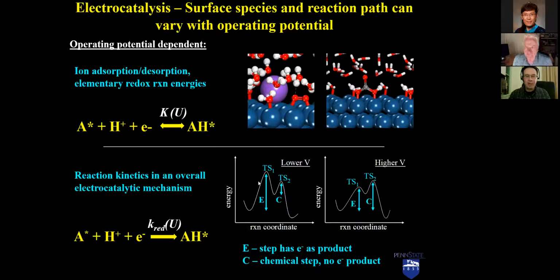Anytime we're trying to make out a catalytic reaction mechanism, or how the energy changes as we move from reactants to products, we are going to want to calculate reaction energies. If those were reaction free energies, then they would give us equilibrium constants. So we want to know elementary step equilibrium constants. Of course, we also want to know the barriers to reactions occurring. Those are activation barriers. And we'd like to then, of course, be able to relate those activation barriers back to rate constants. And if we knew the equilibrium constants and the rate constants, we'd be able to predict the overall rates of reaction with some form of kinetic model.